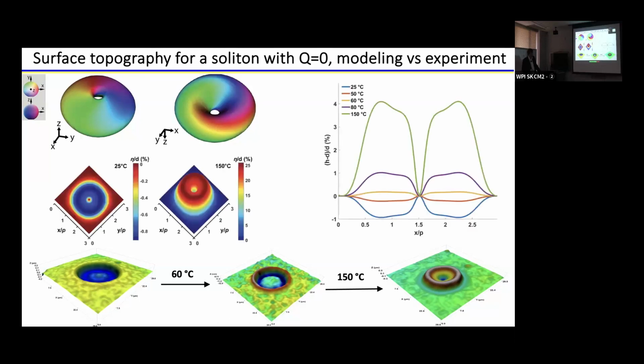Yet another example of soliton that I would like to show, which is purely non-singular, and it has closed loop preimages, but they are not linked. So the Hopf index in this case would be 0, but such solitonic structures are stabilized purely by chirality of the system because they embed twist locally. And so again, for this configuration where you can see preimages tiled together into Pontryagin-Thom constructions that are viewed from two different perspectives, we can see that, again, upon change in temperature, we can control very peculiar features of topography. And then again, these experimental results and computer simulated results are highly consistent with each other.